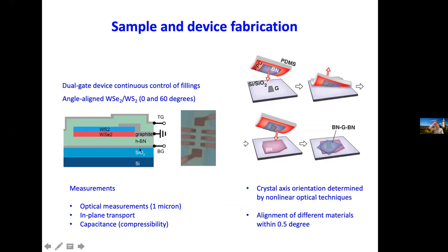Okay, so quickly about sample and device fabrication. We use pretty much a similar technique as twisted bilayer graphene: exfoliate single layers and stack them. Using optical techniques, we can determine the crystallographic orientation of the monolayers, and we can stack them accordingly. Alignments usually can be done with pretty good precision, like half a degree-ish.